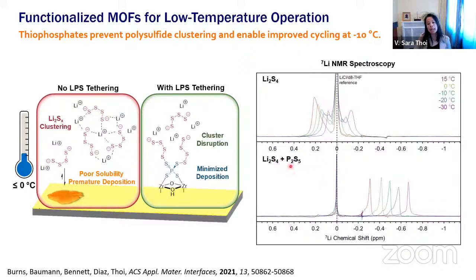But if you take P2S5, which is our proxy for our thiophosphate species, and you add it to that polysulfide solution, you'll see that we still see one lithium environment. And that peak does shift right as we lower the temperature, but it always stays as a single environment. And so this is our clue that we think the thiophosphate must interact with the polysulfides in ways that the solution doesn't at low temperatures.